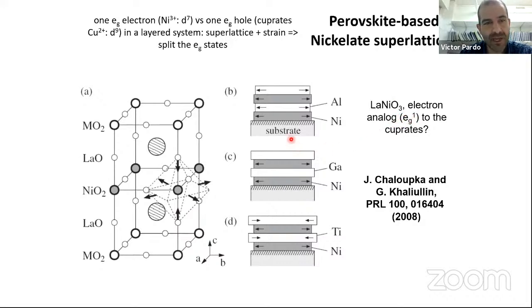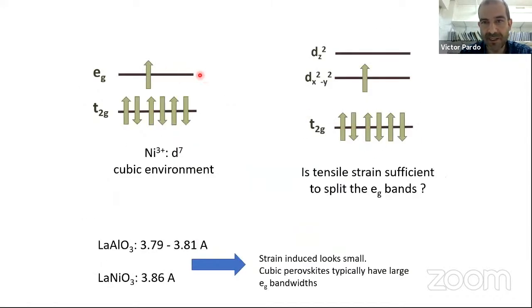And what they said is, okay, we can grow lanthanum nickel O3 in thin films, and with a substrate, we can strain this octahedron, we can enlarge it or compress it so that the eg levels become shifted in energy. The situation would be something like this. They can try to create artificially with strain something similar to the Jahn-Teller distortion that naturally appears in the cuprates. So they say, okay, we can split these bands via strain and get a single band picture similar to that of the cuprates, but instead with one hole, just with one electron.